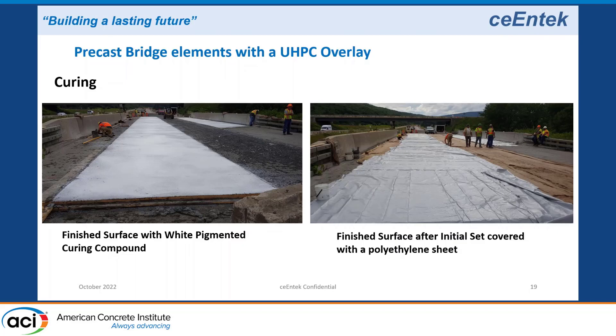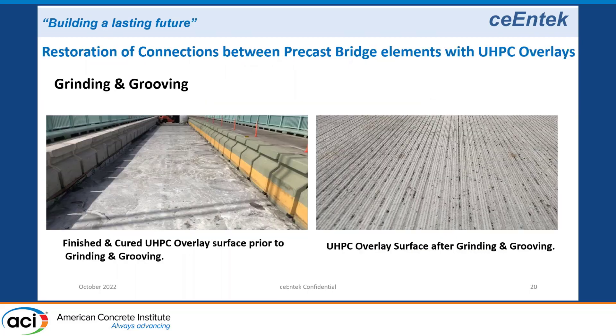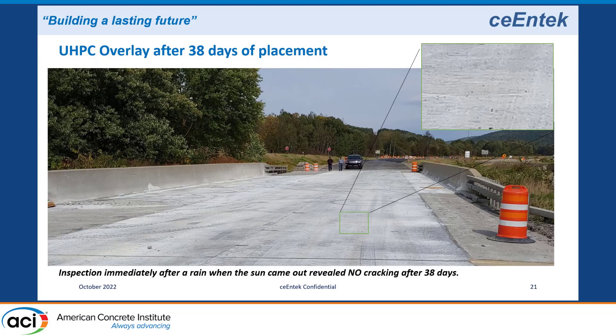After initial set, polyethylene was placed to further protect the overlay. I get questions about whether curing compound alone is sufficient — the answer is no. The following morning there was a lot of condensation under the polyethylene, confirming that moisture was escaping. Since there's no bleed water, keeping moisture in the material is critical to minimize shrinkage. Once the overlay reached about 10,000 psi the polyethylene was removed, and at about 14,000 psi they went in to grind and groove the deck.